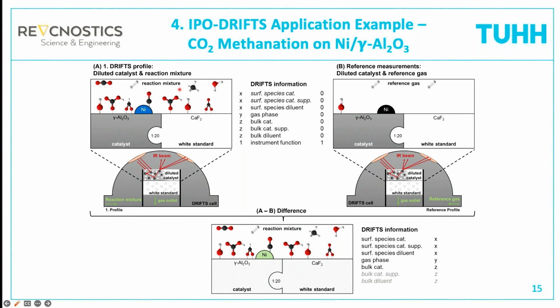Then we have the gas phase molecules. They will also absorb the IR light. We have CO2, we have methane, we have water. These are all strong absorbers, and this will also change as we go through the reactor. So we call this Y for the absorption of the gas species. And then we have the bulk materials. We have the bulk catalyst here. If this is, for example, nickel oxide, could be, we don't know, then also this would absorb IR radiation. If it's nickel metal, then probably not.